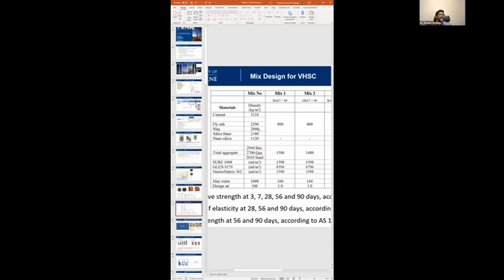For example, fly ash, slag, cement are forged, formed at a very high temperature, so they are crystalline, or the molecular structure is formed well. But CSH we are forming at room temperature. We also know it is more like a precipitation, so the molecular structure is not formed well. That is a weak point. So the whole idea is that if you have these particles like cement, fly ash, silica fume, unreacted, they will contribute a lot to the final result. This is what is happening in very high strength concrete.